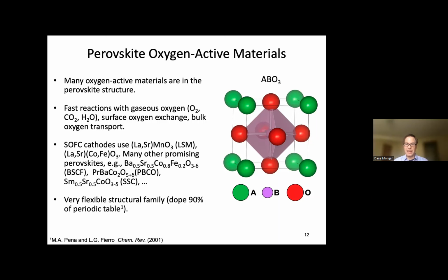There's a lot of standard materials that are used. In fact, lanthanum strontium manganate and lanthanum strontium cobalt iron oxide are the two perovskite materials that make up almost all of the solid oxide fuel cell cathodes that are in use today. There is a significant solid oxide fuel cell industry. Thousands or tens of thousands are sold every year. And they basically all use these two materials, almost all of them, for their cathodes.